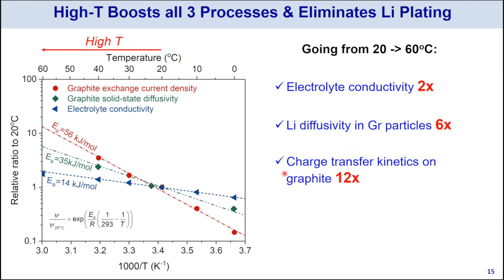And we also develop an engineered interface with 12 times improved charge transfer kinetics. So one single action of thermal stimulation creates three as-if new materials. And that is the power of ATM.